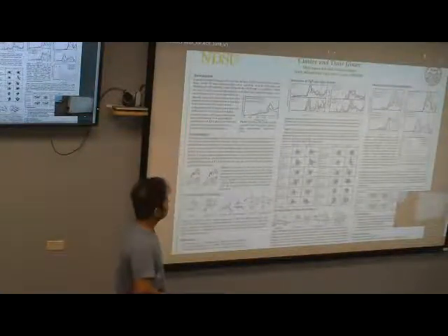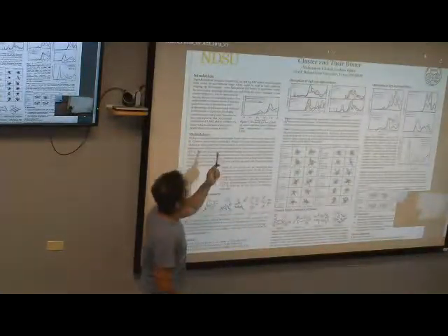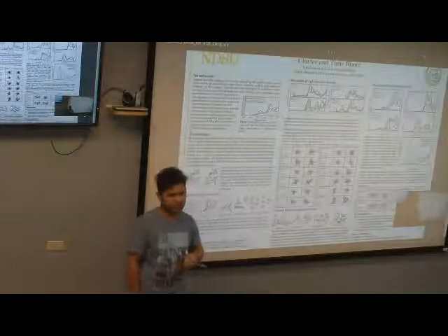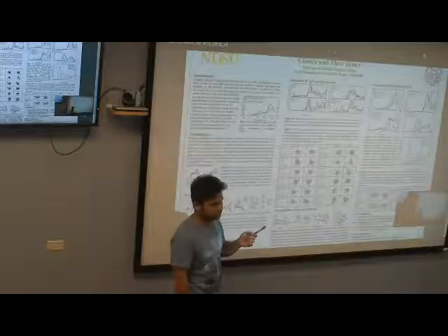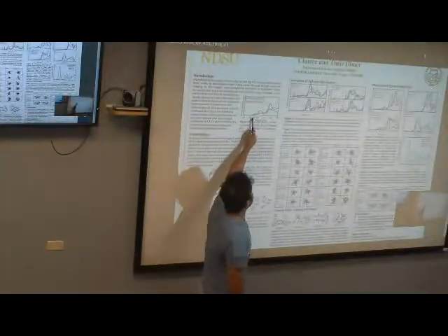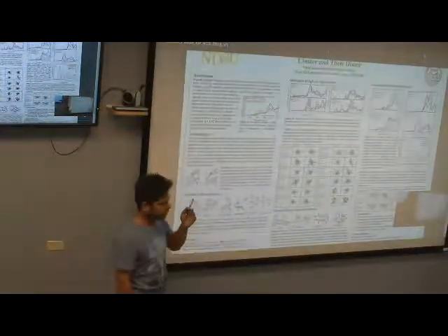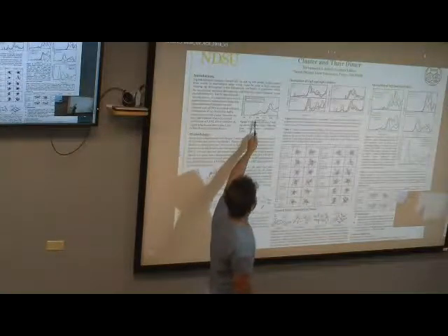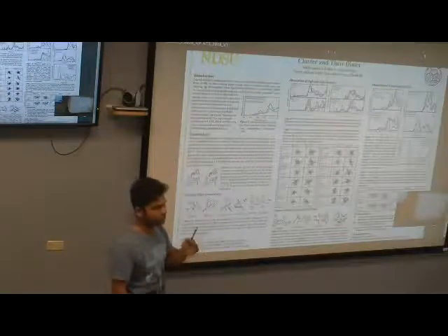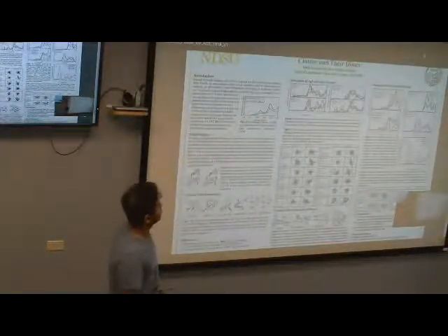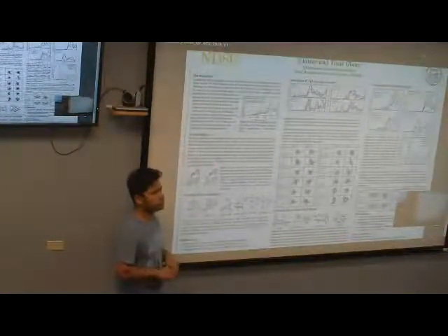And if you look at the absorption spectrum, this is the experimental absorption spectrum. The red line shows the absorption spectrum of the dimer, and the black line is the monomer. They saw that whatever the size of this cluster, when they form the dimer, the lowest energy peak diminishes. It becomes a dark peak, and the second absorption peak increases in intensity specifically, and the third one goes to lower intensity than the monomer. So we started with these experimental results.